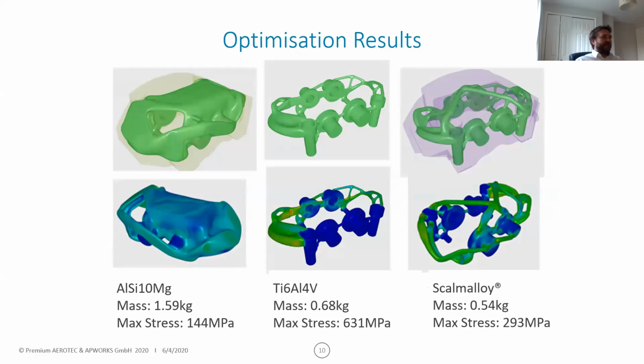And what you'll notice is that they firstly look quite different. The aluminum silicon 10 solution looks really completely different to the other 2 because, to meet the stiffness requirement, it's running into the edge of the design space and having to fill that space with material, which is a good indicator that it's unlikely to be an efficient design, or as efficient as a design that is less constrained by the design space. With titanium 6.4, you can see it's a much more spindly design because we have higher specific properties. Of course, we're running a much higher stress, but we have a much higher yield stress to play with, a much higher design value. And they're at a lower mass.